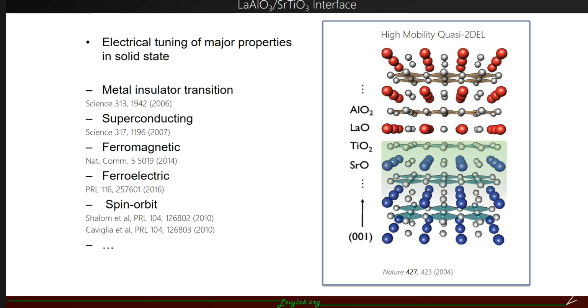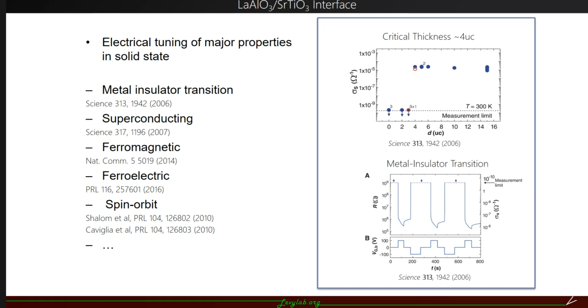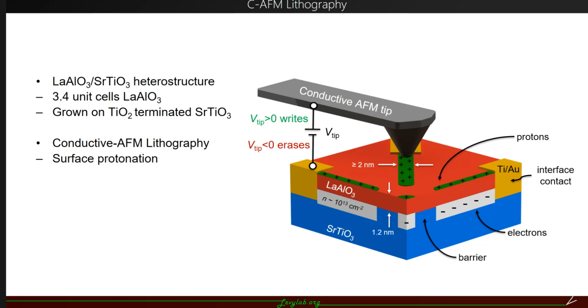Lanthanum aluminate and strontium titanate, which we call LAO-STO for short, are both band insulators. But when we put these two materials together, many interesting properties show up. For example, a quasi-two-dimensional electron gas can be formed at the interface, especially when the thickness of LAO is above 4 unit cells, and this 2D electron gas can be tuned by applying a back gate. With the conductive AFM lithography technique invented by our group, we are even able to write nanostructures at the LAO-STO interface.